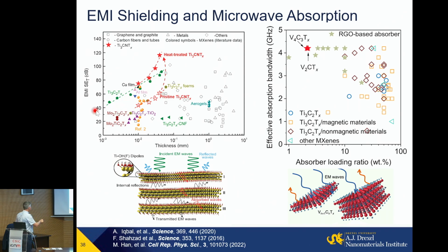Ti3C2 MXene appeared to line up with copper and aluminum in its ability to shield. But you remember I showed you this freestanding film you cannot make easily from metals. Micron thin. 50 decibel means like 99.999% of microwaves will be shielded. You can do it with a 1 micron film. We can go to practically useful for many personal electronic devices, 99%, 20 decibel with 40 nanometer films today. This paper was published in 2016. Within 5 years, it became the most cited paper in the entire field of EMI shielding.